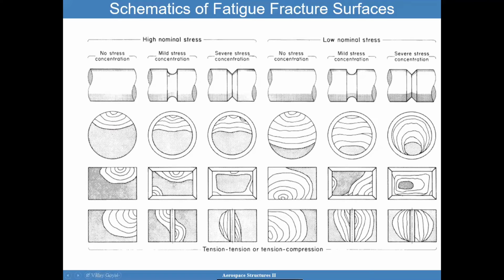In a milder stress concentration, the beach marks are going to look a little bit different. It's going to look more propagated compared to the first condition, and they're going to have less uniformity. As you can see here, this looks like a set of concentric semicircles or arches. And here you're not going to see that. You're going to start seeing some amount of crack propagation going a little more accelerated towards the edges. Why? Because I have a stress concentration, so it's going to cause the crack to also propagate more towards the edge.